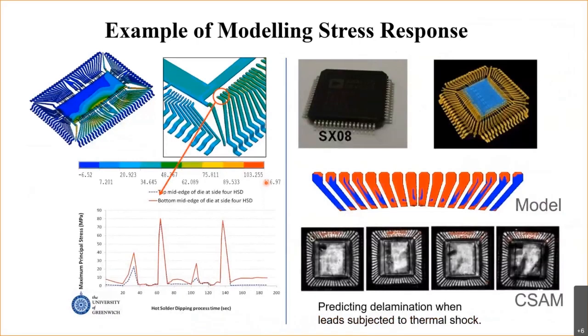And then, of course, as I mentioned before, what type of stresses is the process putting into the package? And here we could see the calculations of the stress, these peel stresses here, as we go through different stages of the dipping process. So where you'll see here the peaks in stress, that's when the side of the package is dipped into the solder bath.